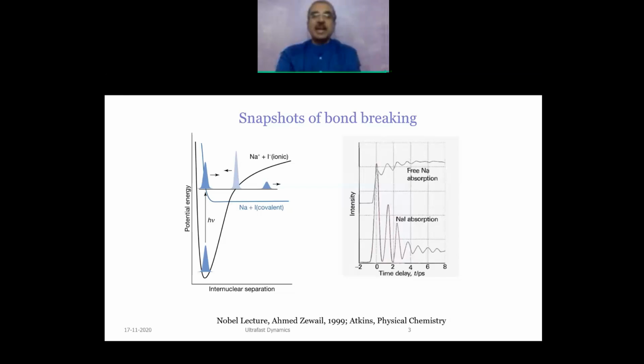And if you look at the x-axis, full scale here is 8 picoseconds, which means within 8 picoseconds, it is all done. Not only that, you see that it is not a smooth decay. It is not a smooth rise. Rather, what you see is some oscillation. What that tells us is that sodium iodide doesn't just break like this. It tries to break, and then the atoms come back, tries to break again, comes back again, and slowly, with every iteration, the separation increases until the atoms are set free.